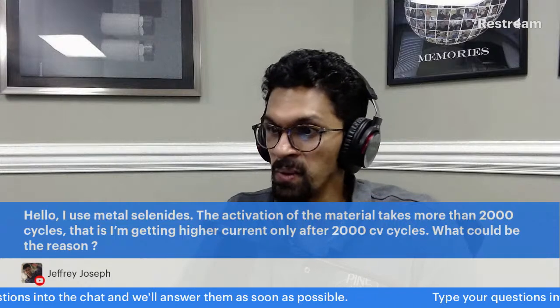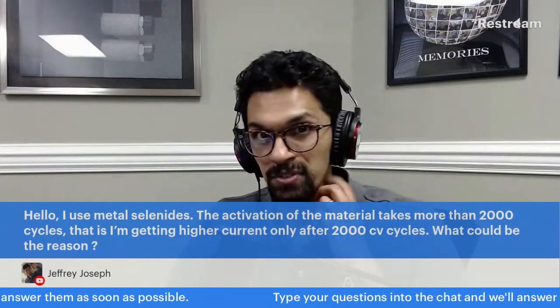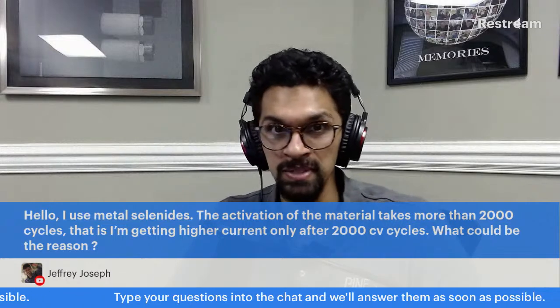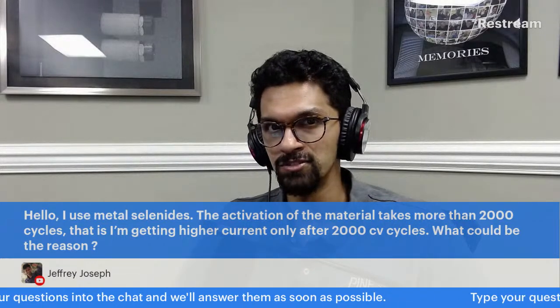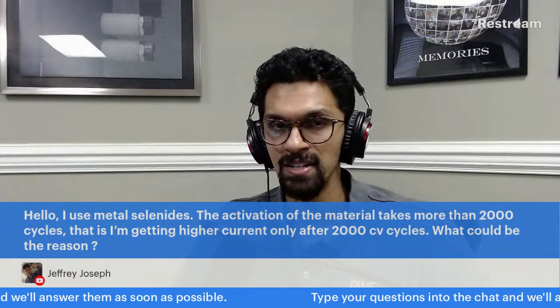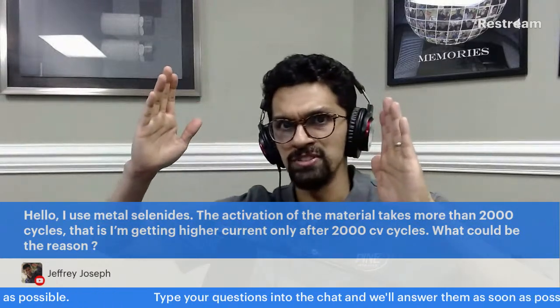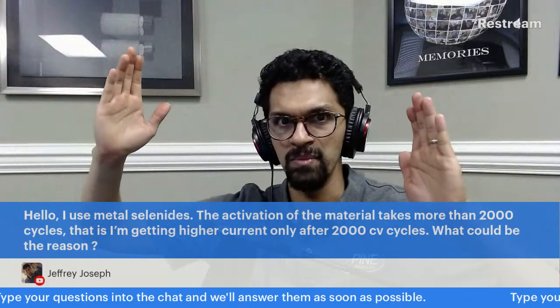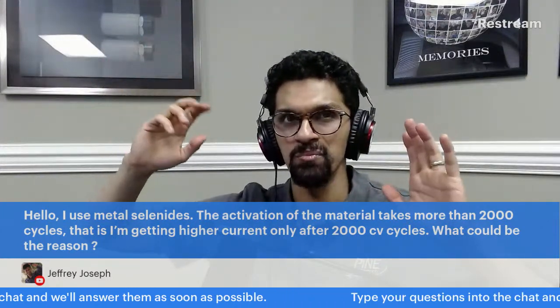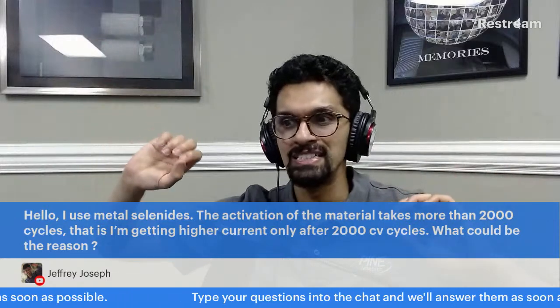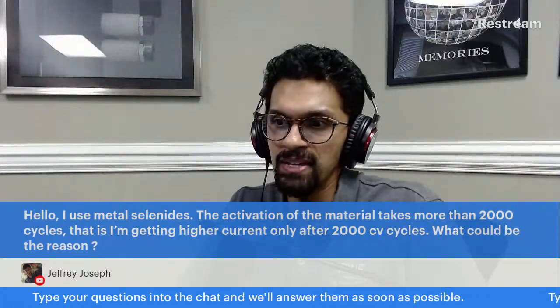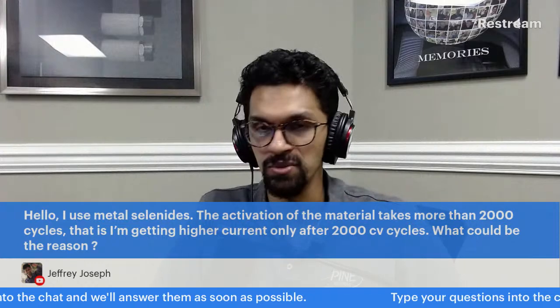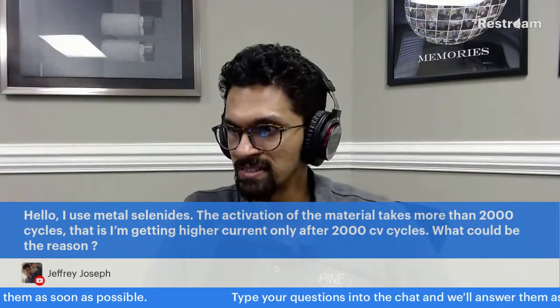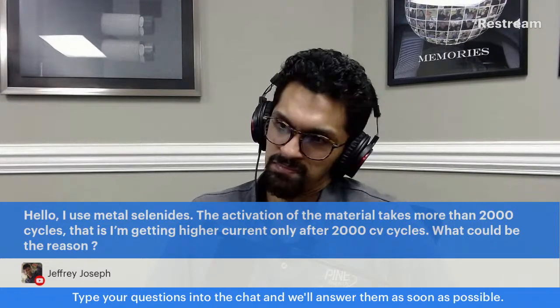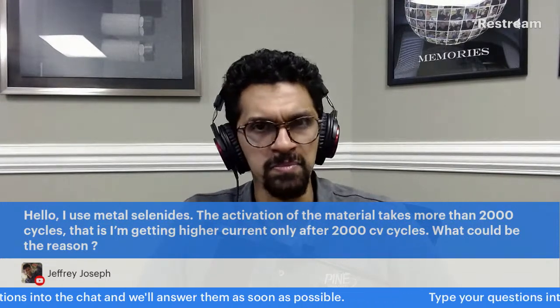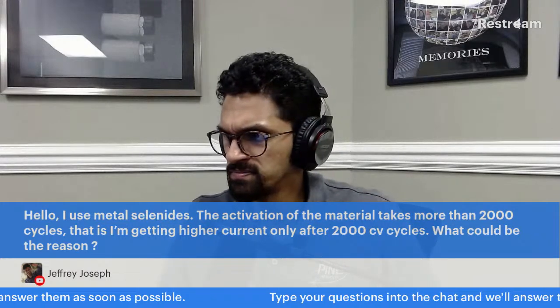Only after 2,000 cycles. One thing you may want to try is going to a higher negative or a higher positive potential when you're doing these cycles. That might be able to decrease the number of cycles, because when you move the potential window of your cycling slightly more, you're hitting your electrode with a more positive or more negative potential to get rid of those extra things. So that may be another reason why so many cycles are required to activate your metal selenide. So hopefully, Jeffrey, that helps answer your question.